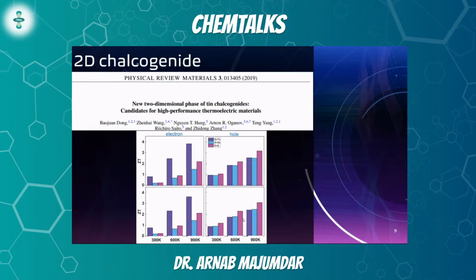Okay. One more example would be another 2D chalcogenide, but this time it was tin chalcogenide: tin telluride, tin selenide, tin sulfide. It was a theoretical paper, but nevertheless, you can see that the SnTe, the purple bar, reached a ZT value of almost 4. Now, this is huge, albeit in theory these values could be quite overestimated. If we did this in experiment, probably these values would become much lesser, but it would still be quite high. So this was quite promising. Now, taking cue from these previous studies, we came up with an idea as well, how to further advance this field.